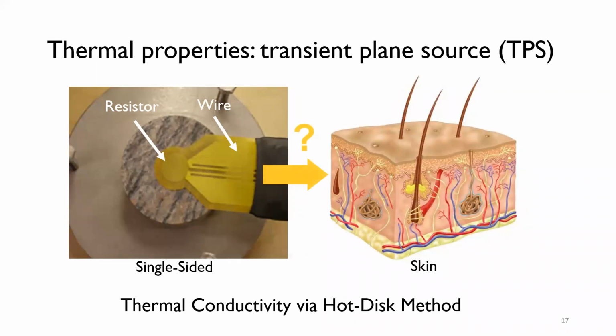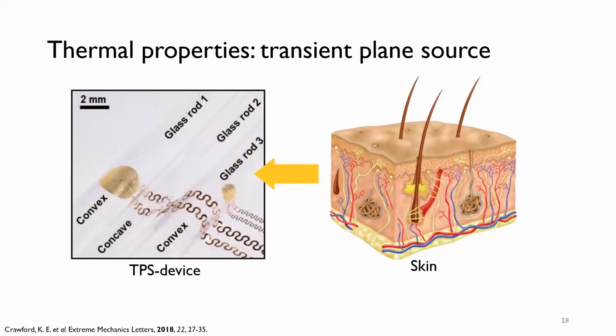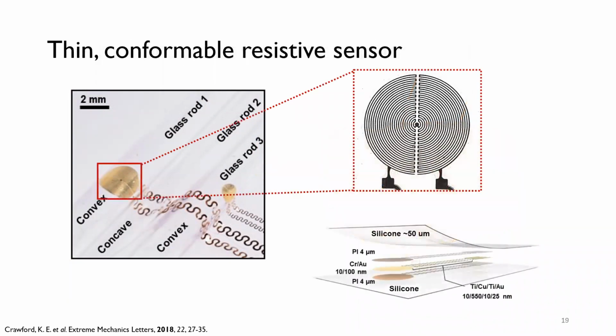All right, well, can we take this from industry? That's what we wanted to do and translate it to this ultra thin device that I've been talking about. And this is an example of a device that I worked on, and we use the serpentine coils, so that allows some degree of stretchability. Metals are not stretchable, but if you give some architectural difference, then we can have some stretching. And then we put a coil, a labyrinth coil for the resistor component. And you can see from this image that I snaked it through some glass pipette tips. So they're like little glass rods. So you can see that it can be concave or convex, and that should laminate very well to the skin. And you can't see this in the image because it's transparent, but it's laminated on a very thin, transparent silicone substrate. And so that would stick to the skin very nicely just through van der Waals interactions. No other adhesive is there.